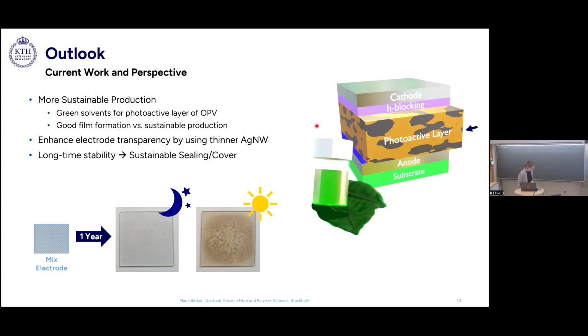What I'm also currently working on is to enhance the transparency of the silver nanowire electrodes by using nanowires of a thinner diameter. And finally, in the picture below here, we did a long time stability test. So this is again the mixed type, the winner from the second part of my presentation. And I stored this electrode under ambient conditions, so room temperature, everything. But one was stored in the dark, and the other one was stored at daylight. And you can immediately see the drastic effect of the UV radiation. And it was also seen in the conductivity value. So this one here was almost non-conductive.